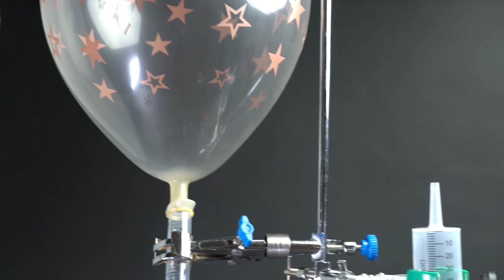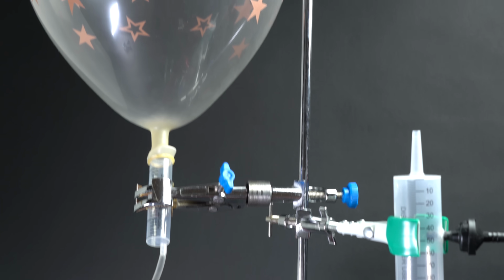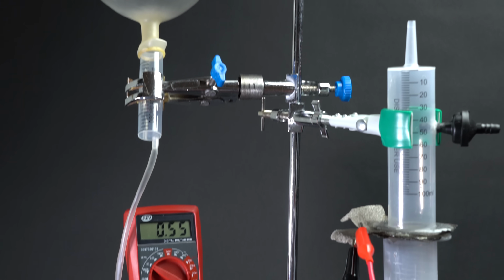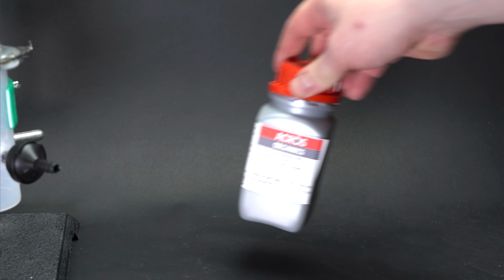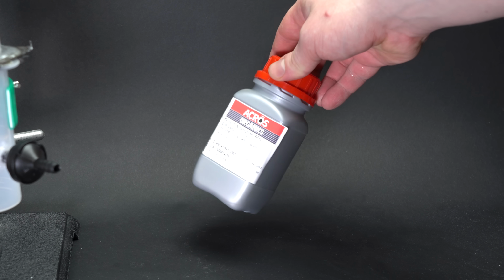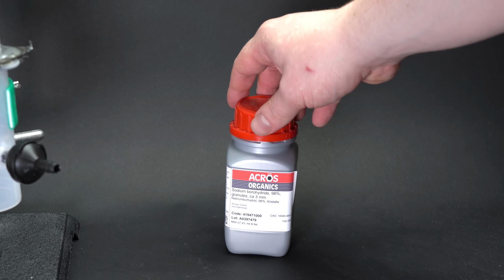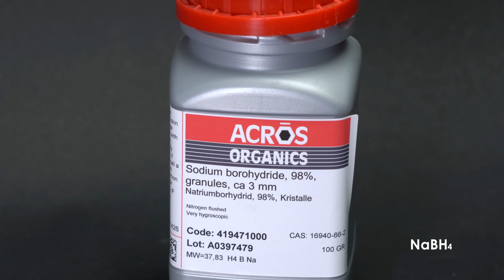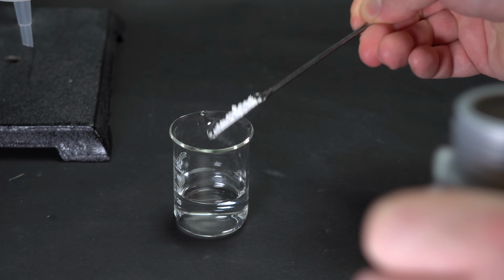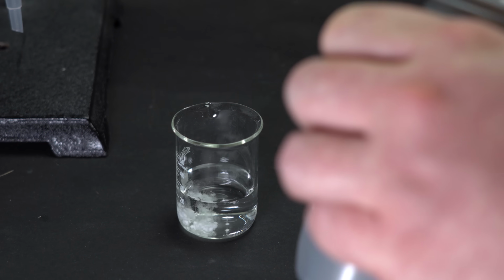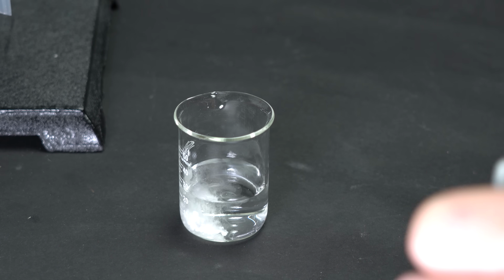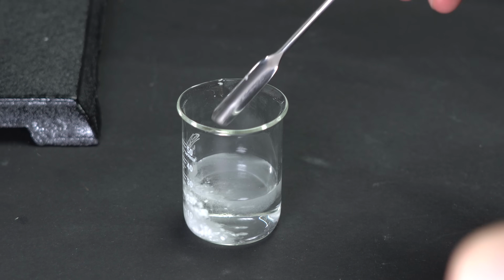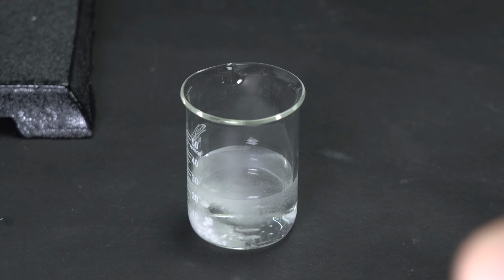The only way to increase the energy conversion efficiency of my battery is to make a more concentrated source of hydrogen. For instance, to use sodium borohydride solution instead. This compound can frequently be encountered at organic synthesis laboratories. It is often used for reducing organic compounds because sodium borohydride easily gives off its hydrogen.